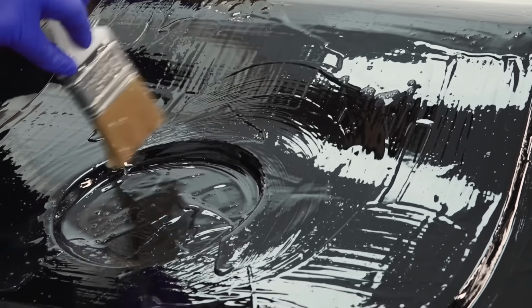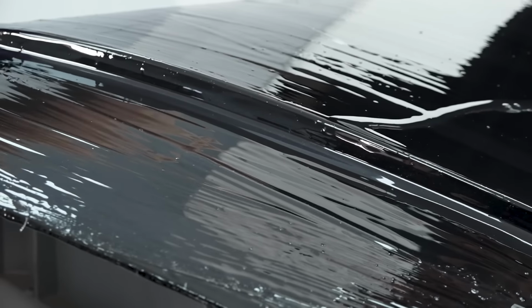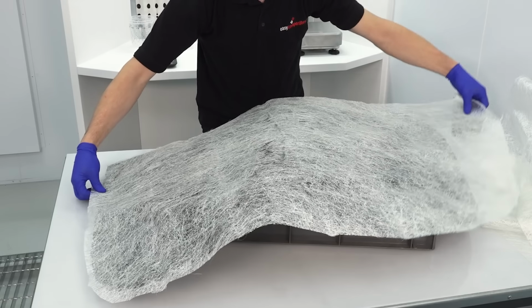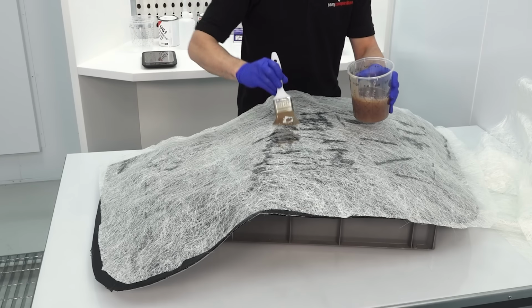Once mixed, a coat of resin should be applied onto the gel coat, and then a layer of the 100 GSM chop strand can be laid down and then further wetted out with resin.